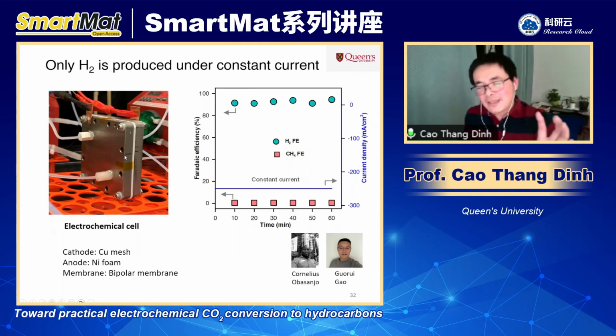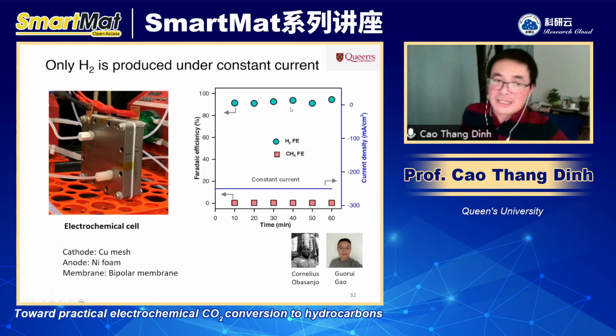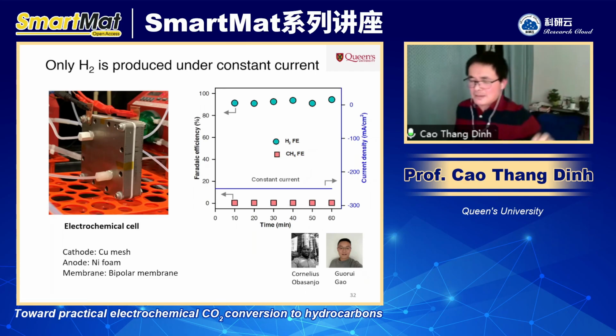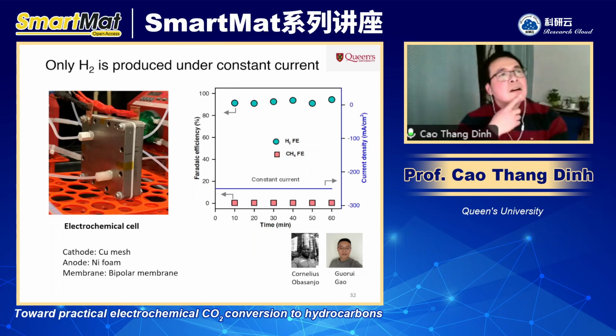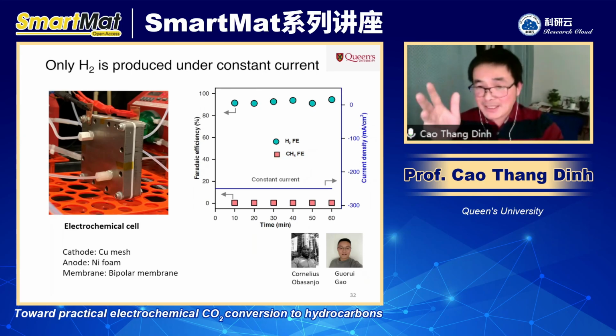The only problem is that when you run the reaction at a fixed current density of 250 milliamp, only hydrogen is produced, more than 90% hydrogen. We did not even see any methane, less than 1%, and no other product. This is a little bit disappointing, but also kind of expected, right?